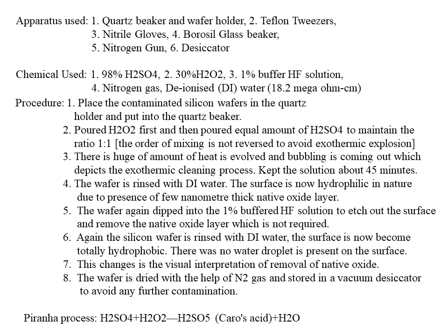Because of that, we are using a quartz beaker and quartz wafer holder. If you use a glass vessel made of borosilicate, this borosilicate glass cannot withstand the exothermic temperature, so we are using the quartz holder and quartz beaker.